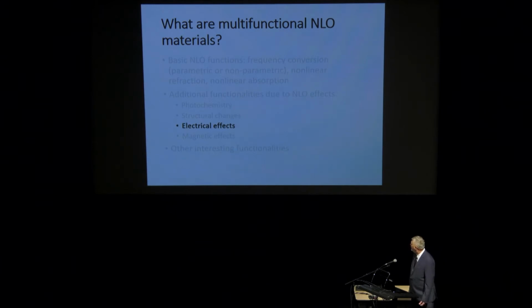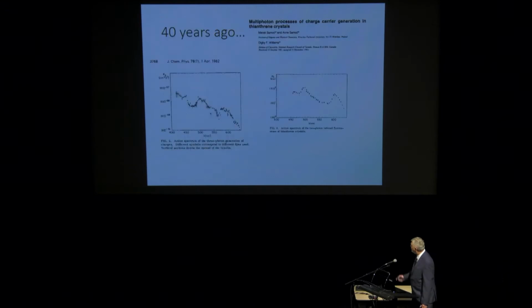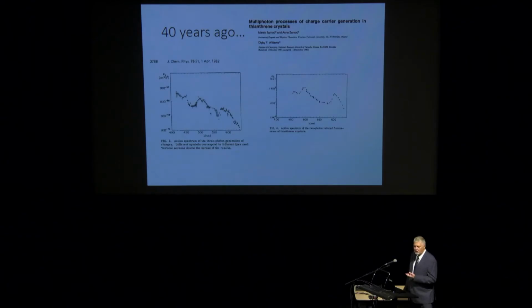Okay, but this multifunctionality, actually, I published my very first paper in nonlinear optics, which was published 40 years ago, about photoconductivity generated by nonlinear optical absorption. So, well, these things have been around for a long time, but perhaps have not really been completely exploited. In this case, what we showed was that you could have photoconductivity in the range where the material is completely transparent at low intensities. At higher intensities, it starts absorbing. Okay, so the mechanism there was two-photon absorption followed by photoionization of excitons. And this mechanism can be quite complicated.